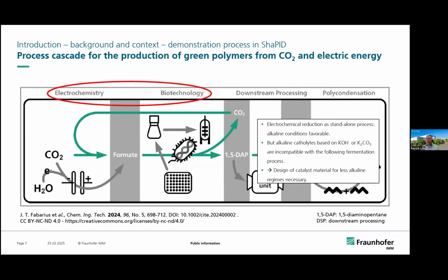Now coming closer to the electrochemistry: since it's a process chain, the electrochemistry approach we are taking, the process conditions and the cell concept we are using, depend on the following step. We are not looking at the reduction as a standalone process, where alkaline conditions are favorable, but we want to use the produced mixture directly in the fermentation process. Alkaline electrolytes based on potassium hydroxide or potassium carbonate are incompatible with the fermentation process. So it's necessary either to design catalyst material more suited for less alkaline regimes, or to have novel process regimes and novel reactor concepts.